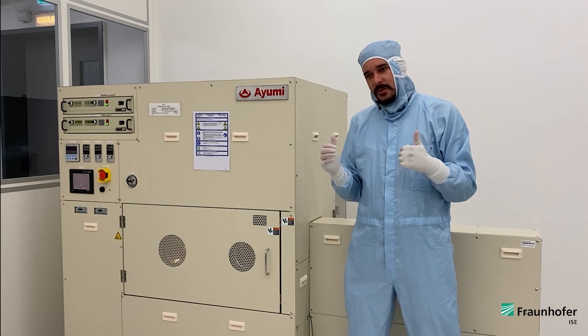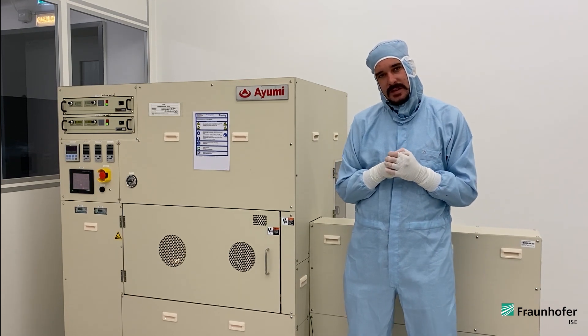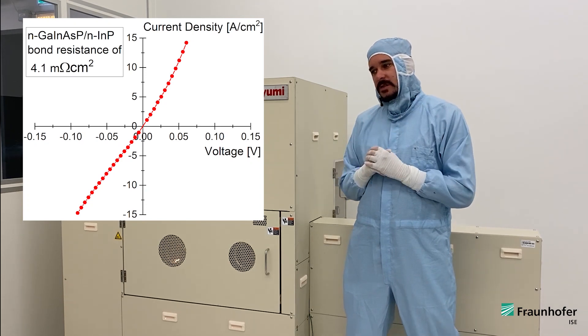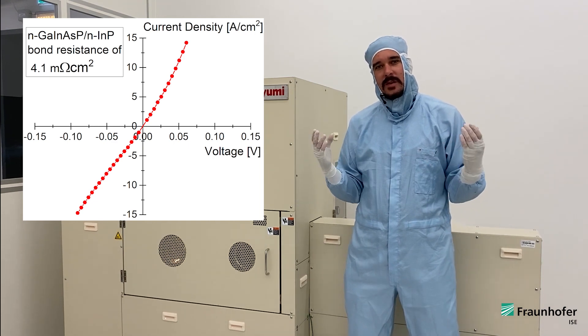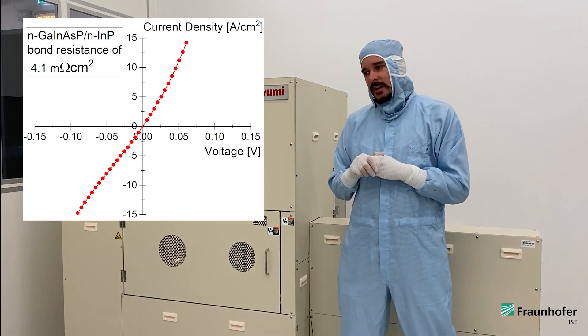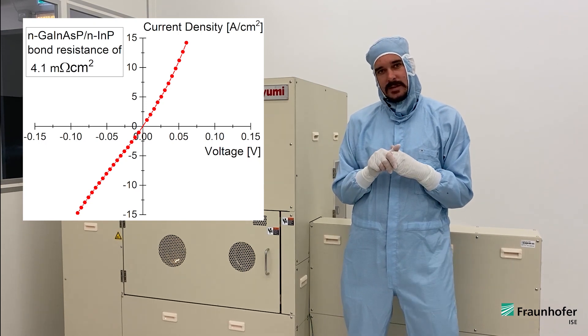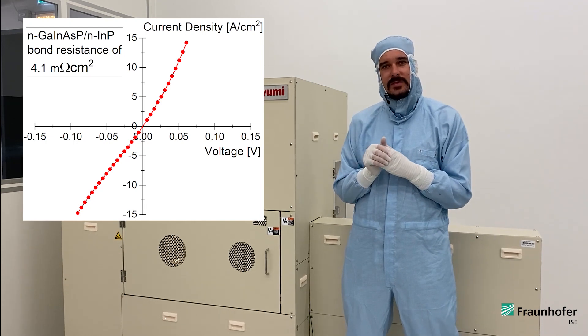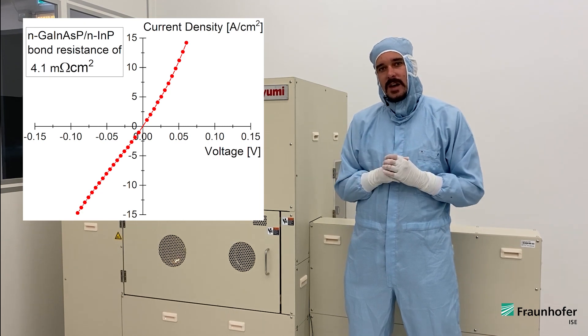The main research focus for the wafer bonding is to minimize the resulting bond resistance. The multi-junction solar cells are operated under concentration at very high current densities, and here already relatively small bond resistance leads to significant voltage losses. We are trying to optimize the process parameters of the wafer bonding itself, as well as the materials bonded to each other, the so-called bond layers.